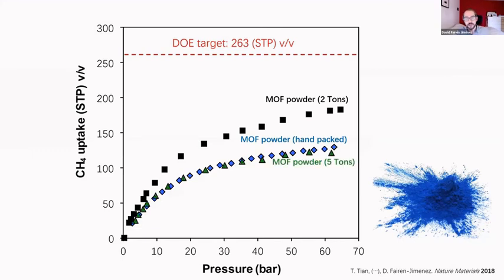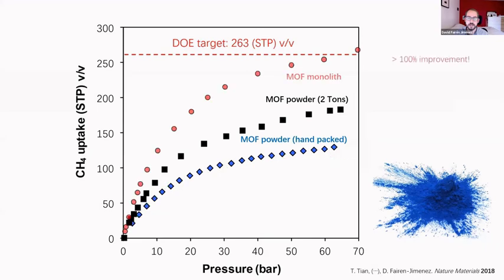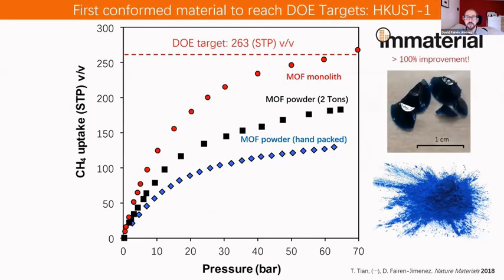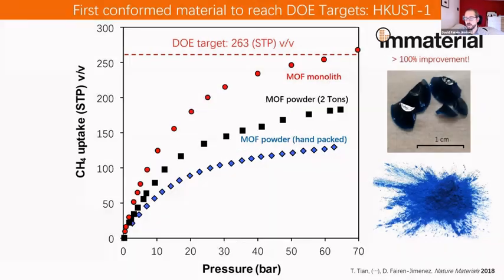They say, okay, let's go to 5 tons. And you see what the problem is now? The green one, when you apply 5 tons, decreases. It decreases because you densify the material, but you also collapse the porosity of the material. Okay, you destroy the sample. And this is the monolithic structure, okay? Basically, a big difference between the powder and now the densified monolithic structure. Much, much higher adsorption capacity than any other material published so far, okay? A 100% improvement versus other powder materials.